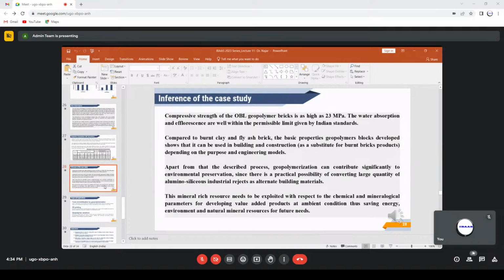The following are the inferences of the case study. Compressive strength of OBL geopolymer brick is as high as 23 MPa. The water absorption and efflorescence are well within the permissible limit given by Indian standards. Compared to burnt clay and fly ash brick, the basic properties of the geopolymer blocks developed show that they can be used in building and construction as a substitute for burnt clay bricks or clay products, depending on the purpose and engineering models.